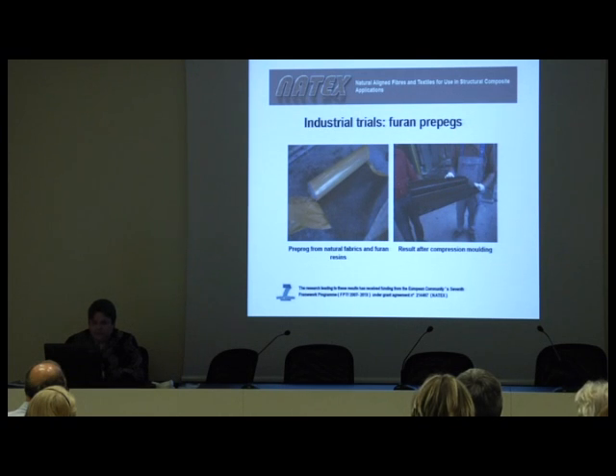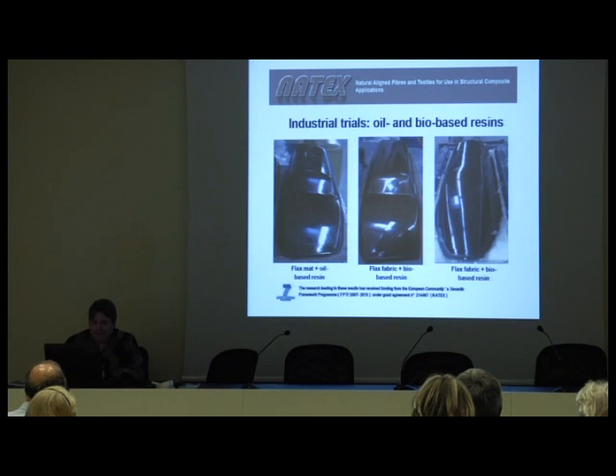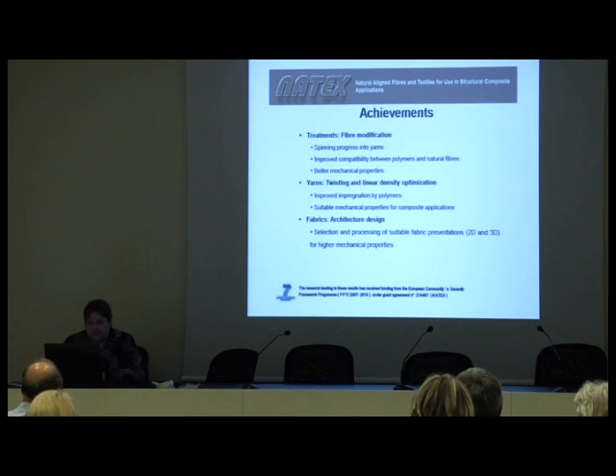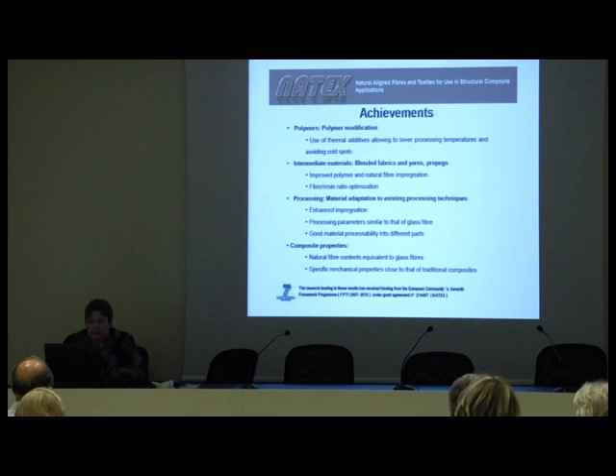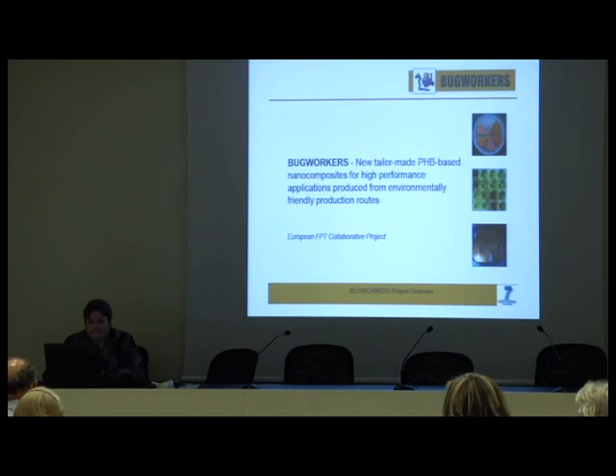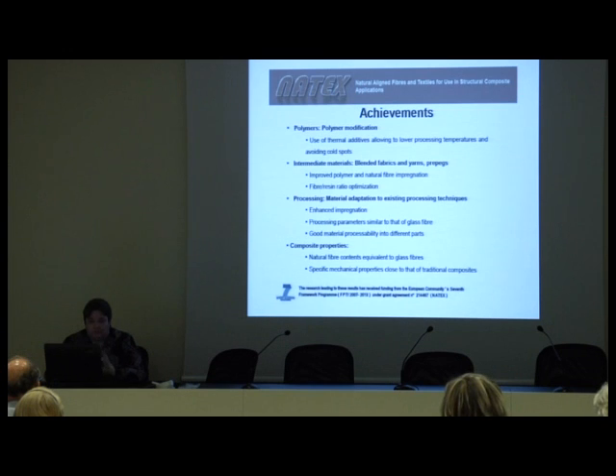These are examples of the prepregs. And these are some of the components. We obtain very good surface results, and also the mechanical properties were quite adapted to the application. So the main achievements: spinning process into yarns, improved compatibility, different architectures. The use of these thermal additives allowed us to reduce more than 20 degrees the processing temperatures. So this is related to the NATEX project.